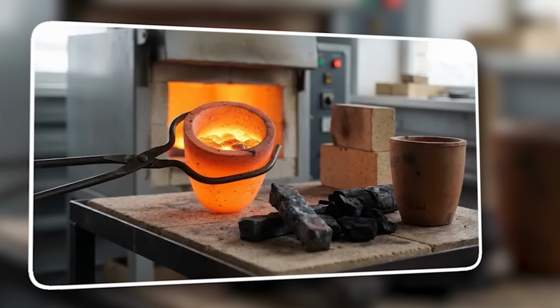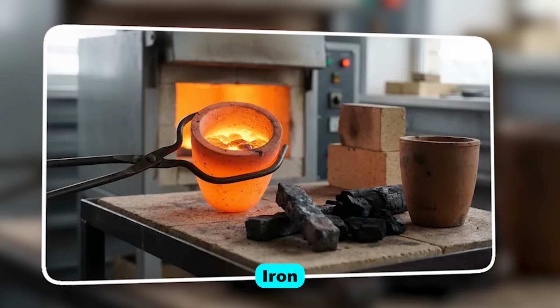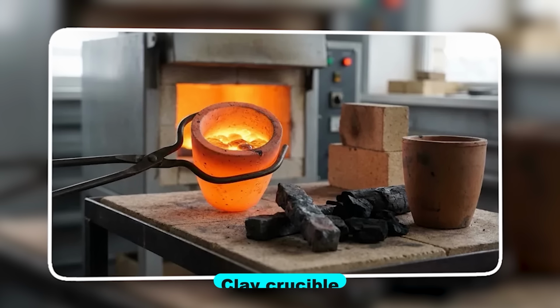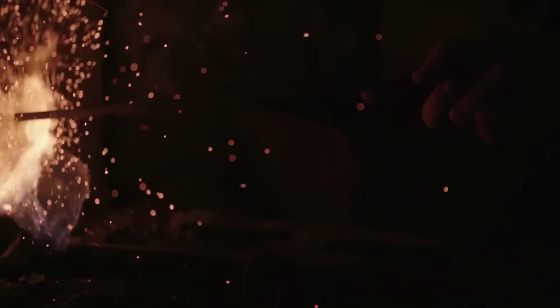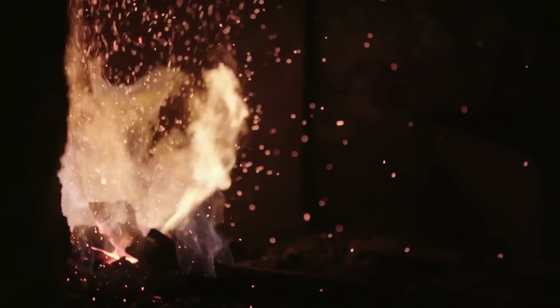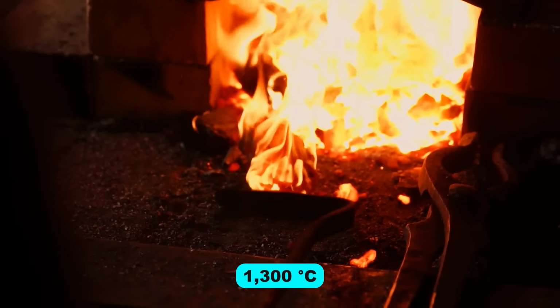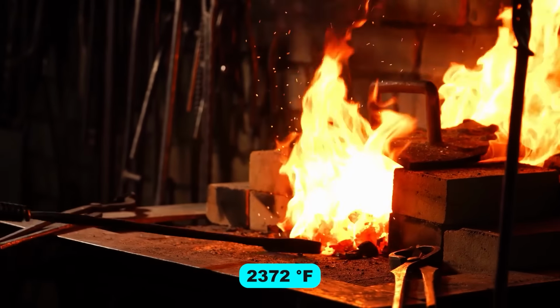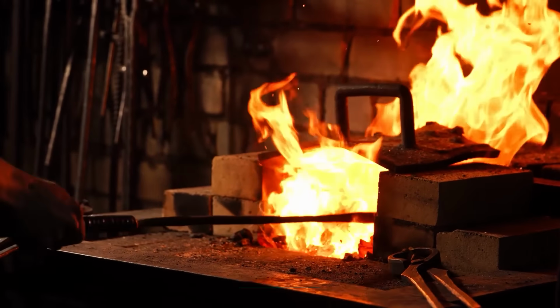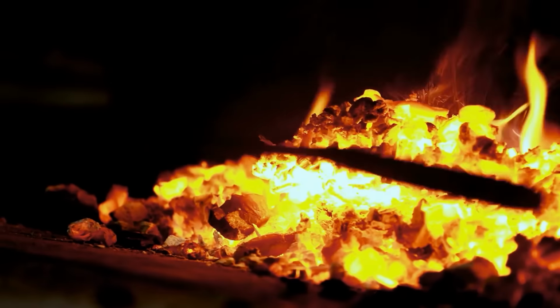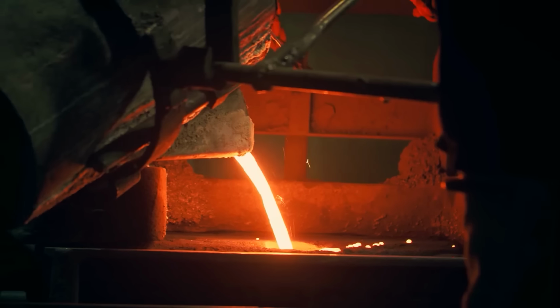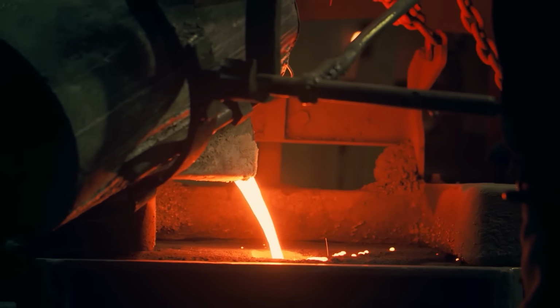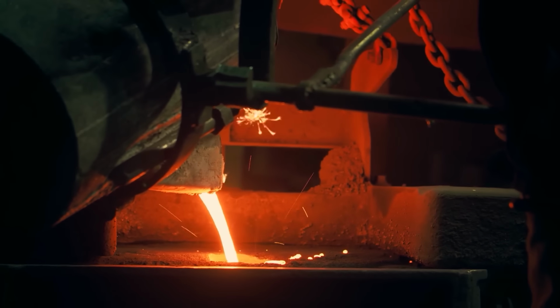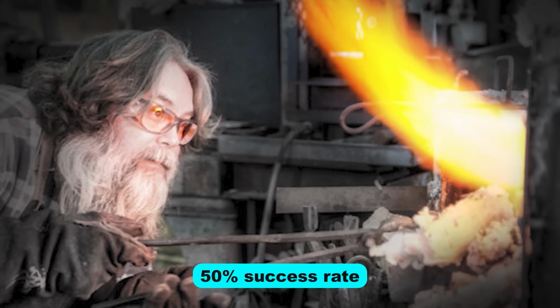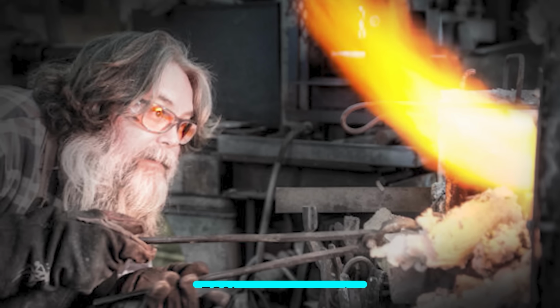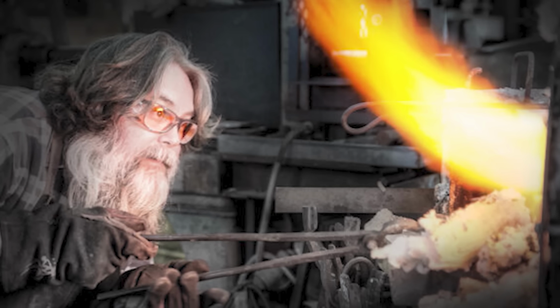In theory, the materials needed to make Wootz are simple: iron, carbon, a clay crucible, and a hot enough fire. In practice, however, the process is extraordinarily difficult because the temperature must reach above 1,300 degrees Celsius or 2,372 degrees Fahrenheit. The carbon content must land in a narrow range, the cooling must be slow and controlled, and without the right trace elements in your iron, you may produce crucible steel but never achieve the banding. Rick Furrer's 50% success rate on forging alone tells you how unforgiving the material remains even for an expert.